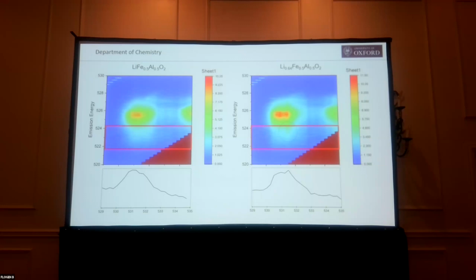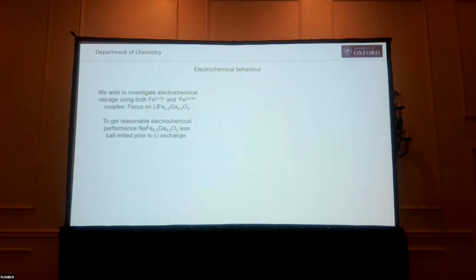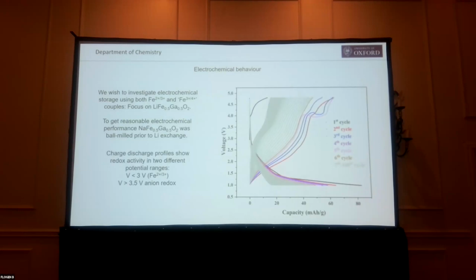Okay, so to finish off with, what about the electrochemistry? Well, what we want to do is ideally cycle iron 2, 3 and then 3, 4, or whatever this anion redox is here. We're going to focus on the gallium system, where the reduced material is also stable. And so if we do a charge-discharge series of cycles, so people are familiar with this format of the data, I'm plotting out the capacity, milliamp hours per gram. This is how much lithium we're taking out at the beginning. So the oxidation would go up, and then the reduction would go down.